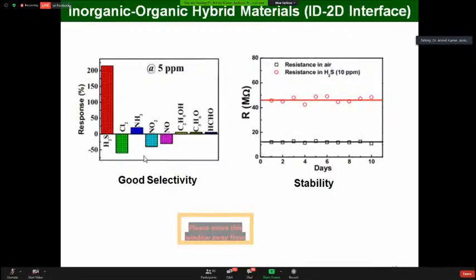Moreover, these heterojunction sensors show good selectivity. You can see that the selectivity is measured in the presence of other gases, and it is very highly selective towards H2S gas. Further, the stability: this is the resistance of the sensor in the presence of air, and this is the resistance of the same sensor in the presence of H2S. You can see the resistance is very stable over time. So the stability of these inorganic-organic hybrid materials is also improving.